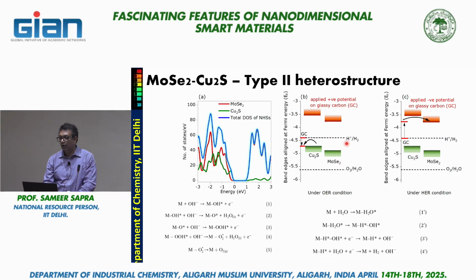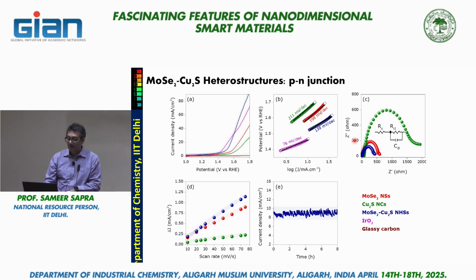Okay. And you align it with the reversible hydrogen electrode, and you'll see that it's possible to get the electrons and holes both out of the system, and therefore do an oxygen evolution reaction and a hydrogen evolution reaction, both from the same material. And therefore, these are the results of oxygen evolution reaction, which surpass the industry standard of iridium oxide. Iridium oxide and ruthenium oxide are the ones that are being used in the electrolyzers today. I hope everybody is aware of the green hydrogen mission. India is going strongly for that, and they are setting up so many electrolyzers.